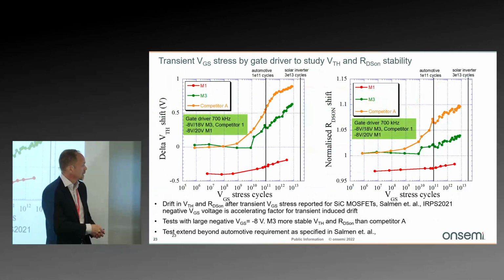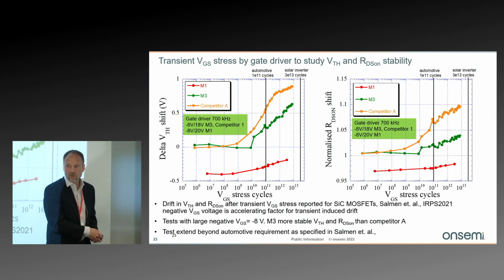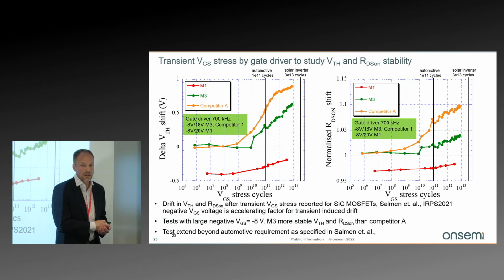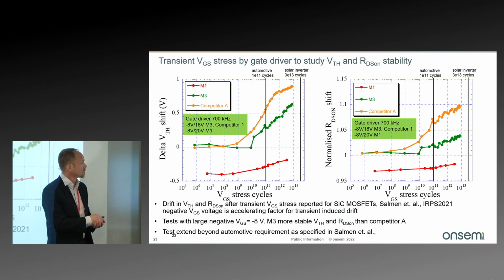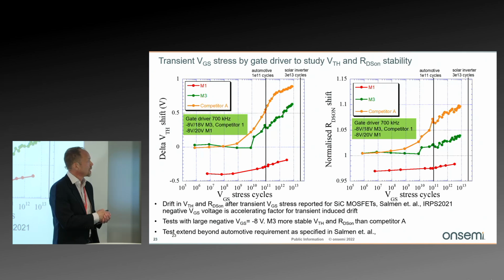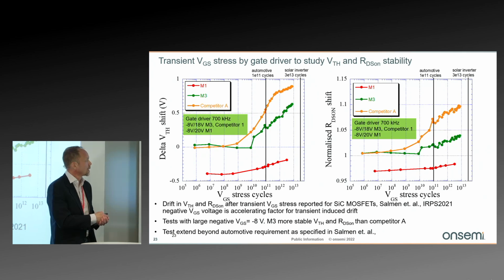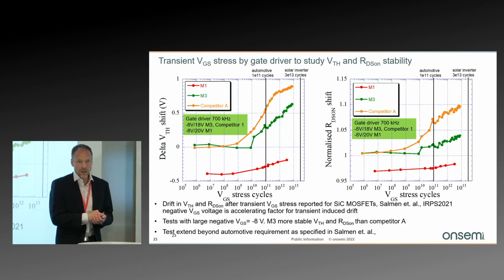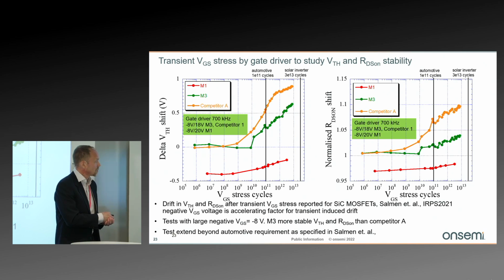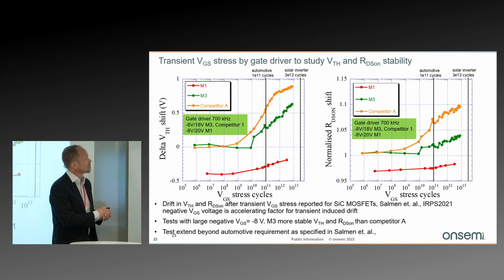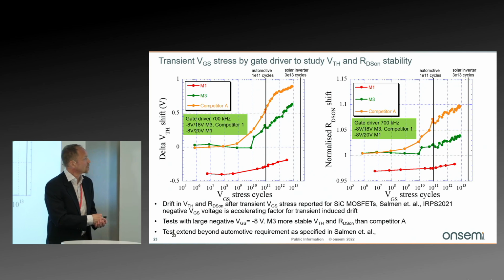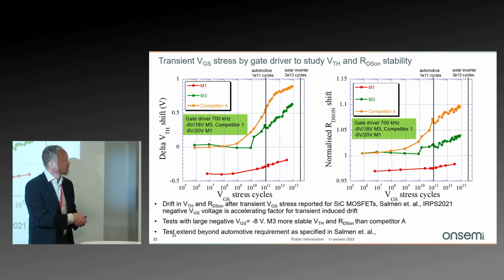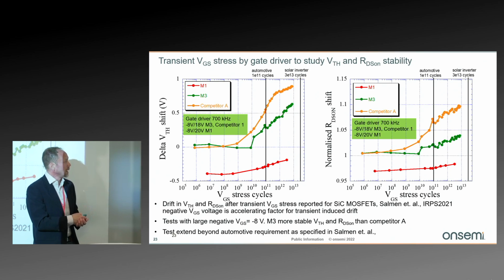We have used -8 volt here, which is higher than recommended in application. And what we do is we run stress at 700 kilohertz between -8 and 18 volt. And then we interrupt and do a parametric measurement of threshold voltage to the left here, and RDS(on) to the right. And here is our M1 and the M3 device, and here is the competitor A.